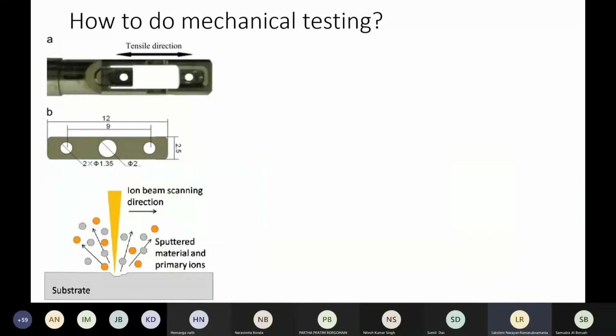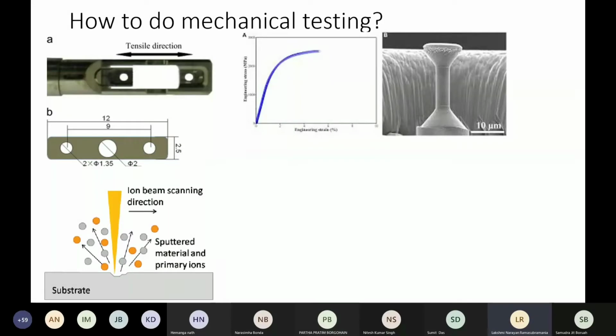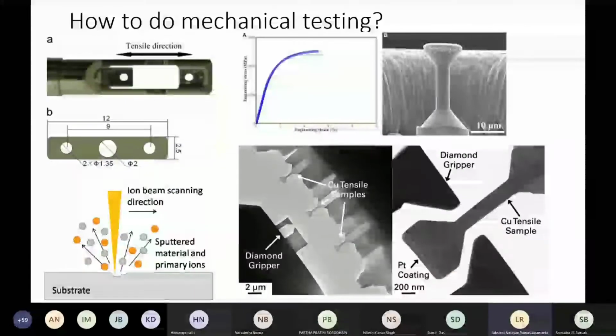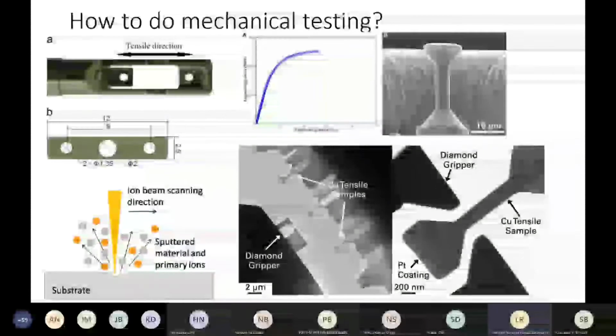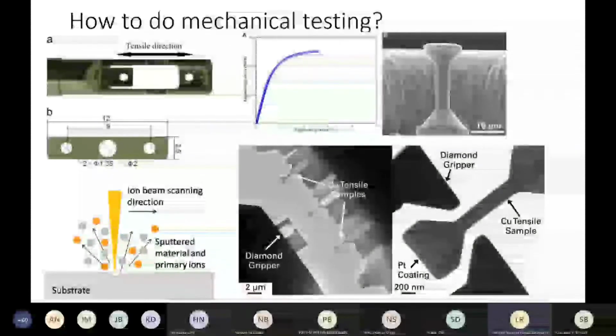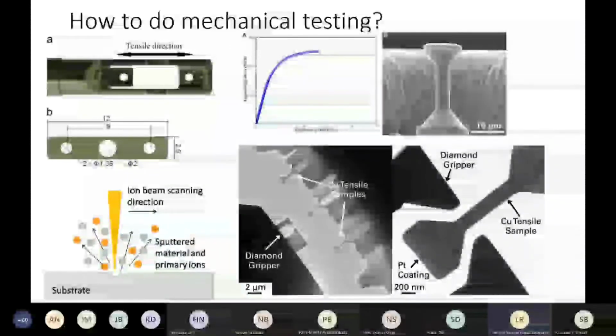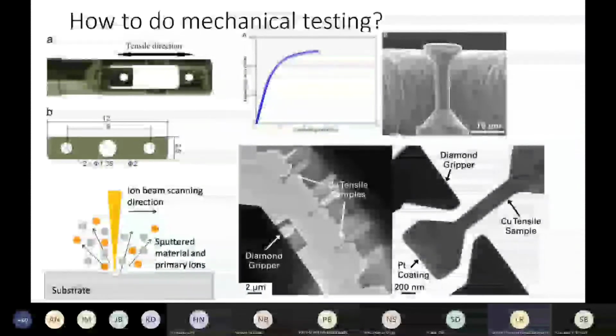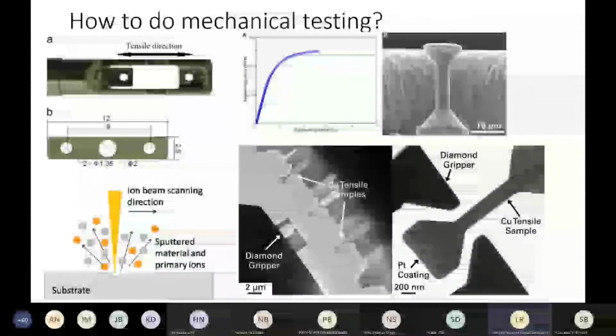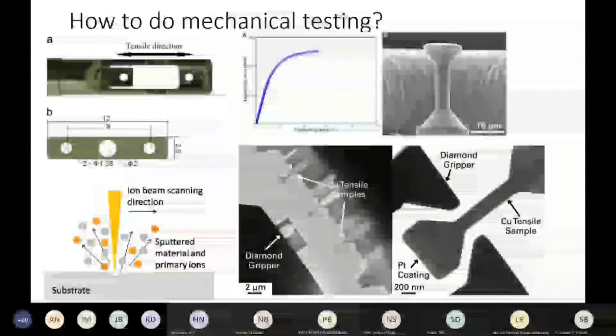And why do we do this? Because we need to form a tensile sample of this nature. This is very nice looking. Look at the scale bar. It is only 10 micron. And you see that this is a very nice cylindrical dog bone specimen. And to do these tests, we essentially have this gripper. This is called a diamond gripper. It's made of diamond, and it can go to the nanoscale level. It can hold the sample in this particular fashion as shown in the right side figure. This is going to show a tensile test on a copper sample.